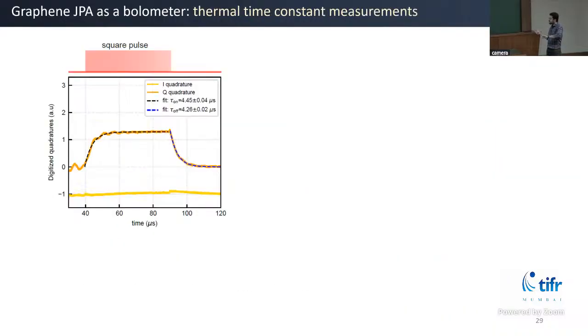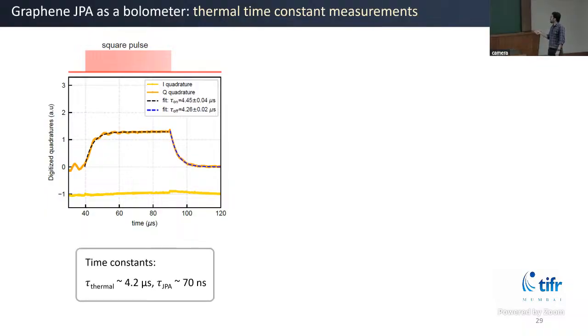Next, we try to probe the time constant of these devices. The second metric I mentioned is the response time of this bolometer: how fast you can heat it and how fast you can reset it back to the cooled state. For that, we do a pulsing experiment. We send square DC pulses that hit the bolometer. This increase that you are seeing is because of the square pulse hitting. Then it takes some time to cool back to the unheated state. You can fit an exponential to extract the time constant of this bolometer, how much time it takes to come back to the unheated state. We found that it is about 4 microseconds, which is fast, but not very fast.